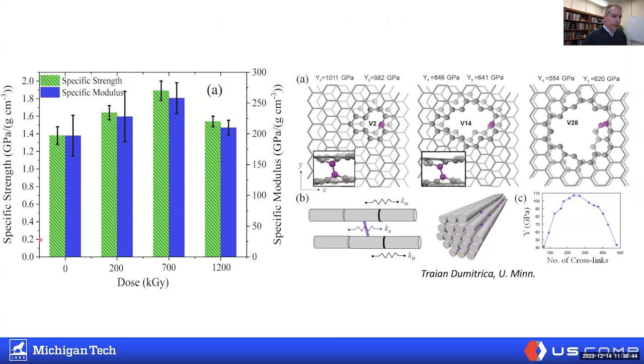You can see the baseline here is no irradiation. And we start to irradiate it a little bit with a 200 dose and a 700 dose. We're able to push up the strength and the specific modulus up to this maximum level. Now, if you get a little bit too crazy with those gamma rays, it starts to slowly degrade the material a little bit, which of course is not desirable. So there's a nice little sweet spot there.